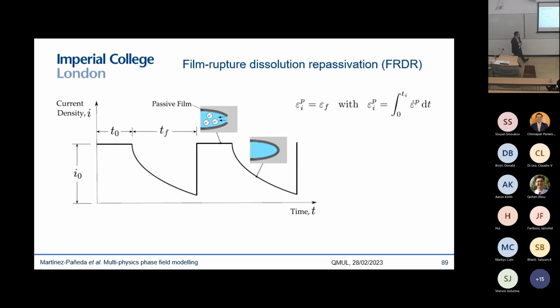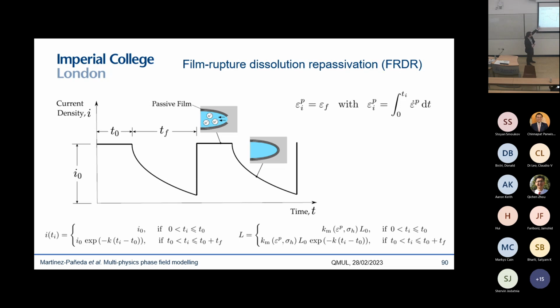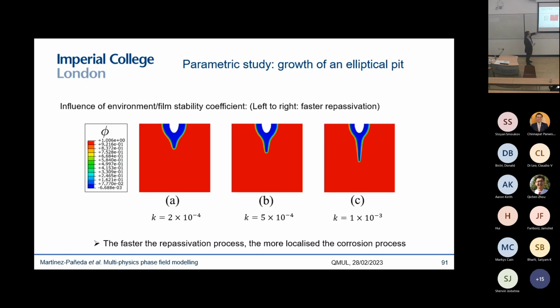Another factor that we have to incorporate, of course, is this film rupture and repassivation mechanism. So typically, many materials like stainless steel will develop a passive film that will protect them from corrosion. But if your mechanical loads are high enough, you will eventually rupture that film, and that's when you get this localized corrosion, until it repassivates again. So it's a competition between crack tip straining kinetics and this repassivation kinetics. And we can capture that easily in our model, so we can capture how we have this film that protects us, and we have a parameter that we can tune to capture this interplay between the repassivation process and the crack tip straining.